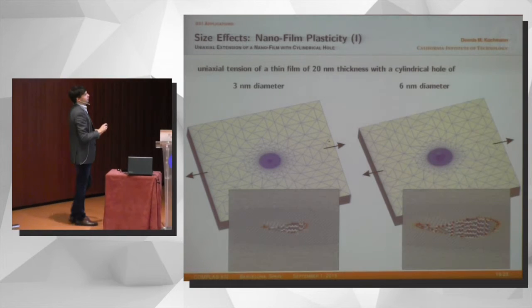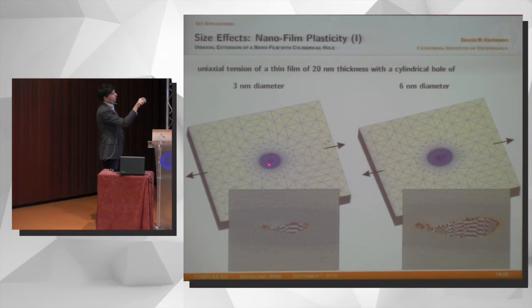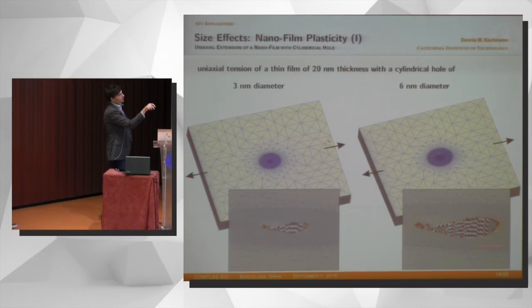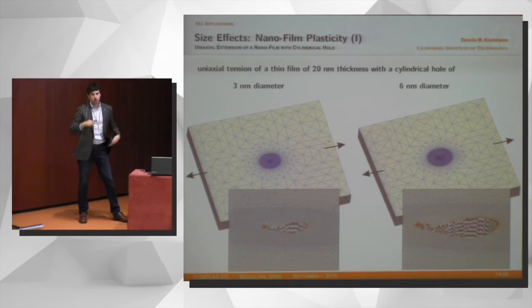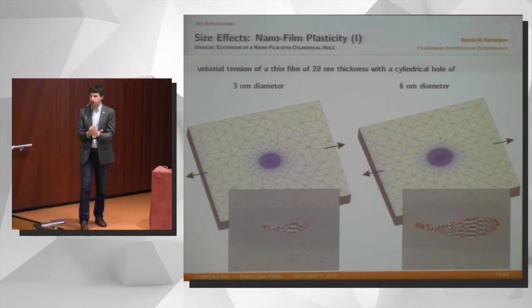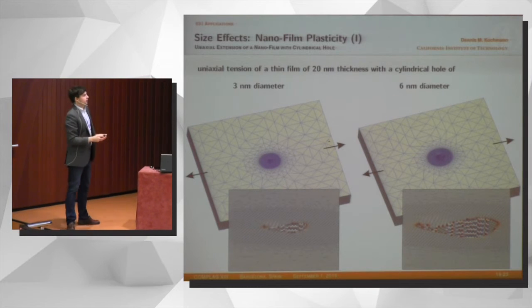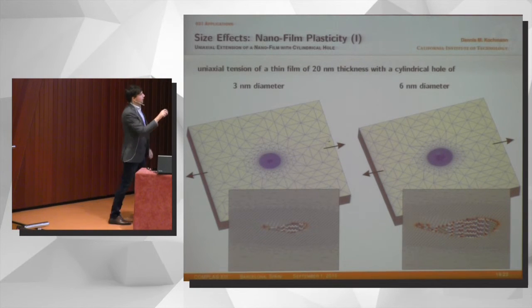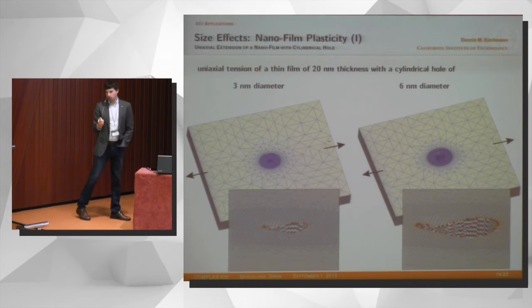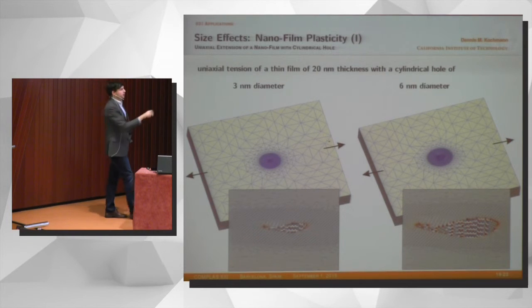If you do atomistics, however, of course the size matters. If you use a small hole versus a large hole, you feel individual atoms. This is a zoom in on the surface, and so you do see very strong and very clear size effects, generally with smaller being stronger. The only way we can run these simulations efficiently is because we have full atomistic resolution around the core, at least at the beginning, and we coarsen dramatically away from the hole. Again, this can be done adaptively, so as dislocations run, you can adaptively refine.